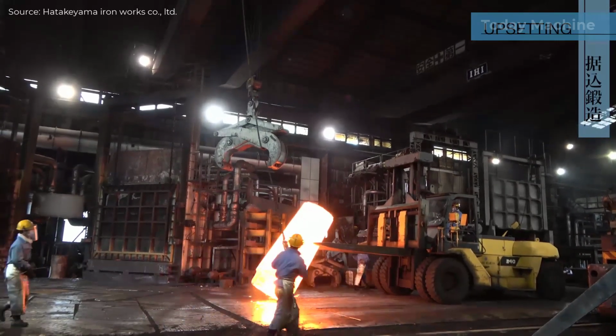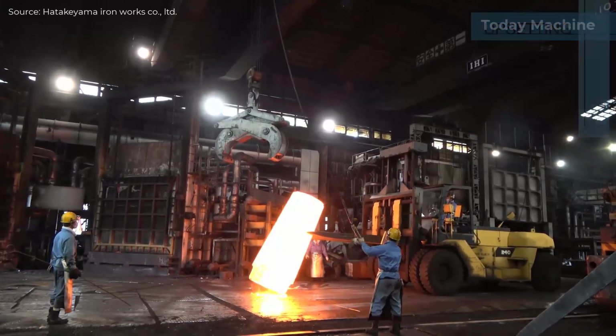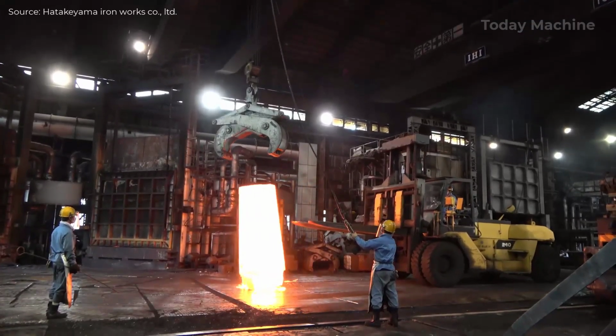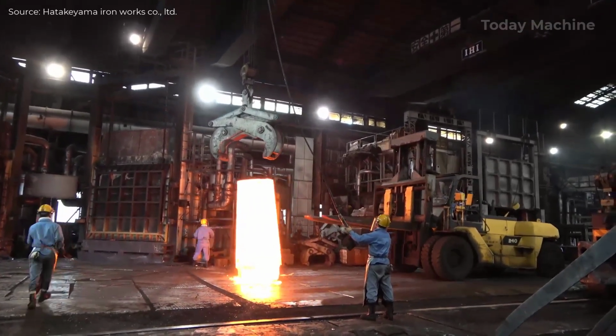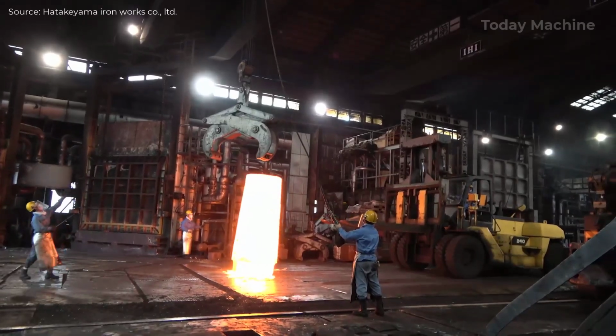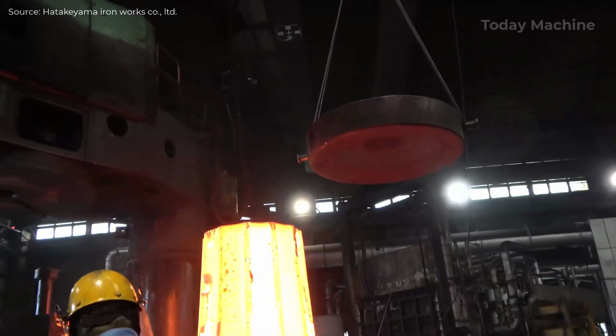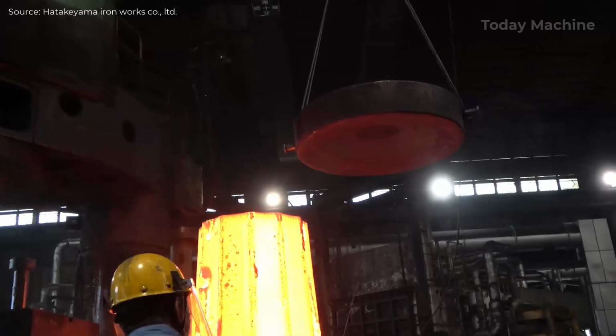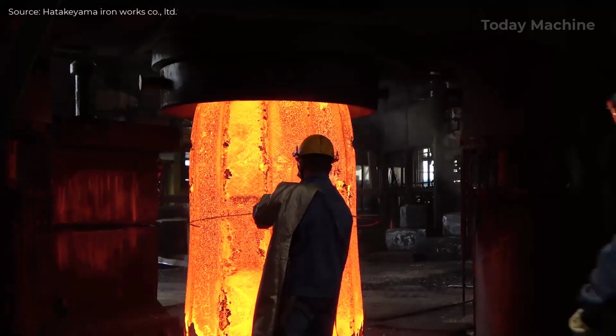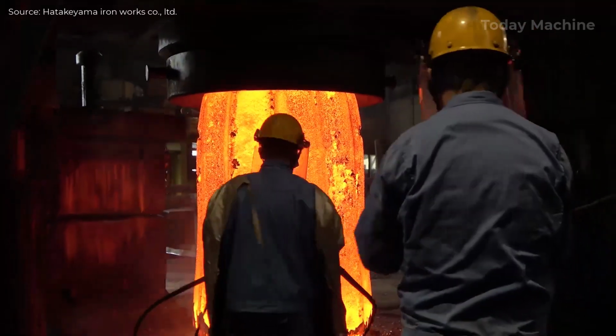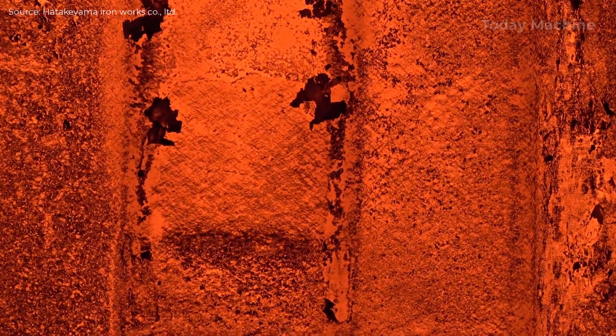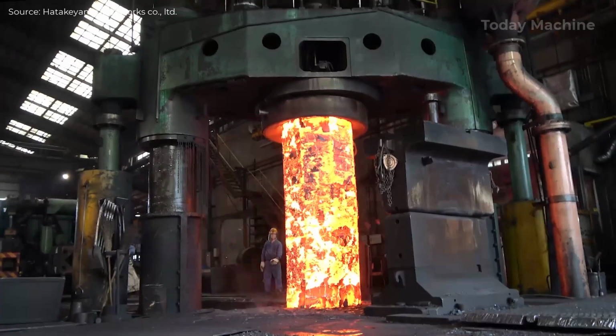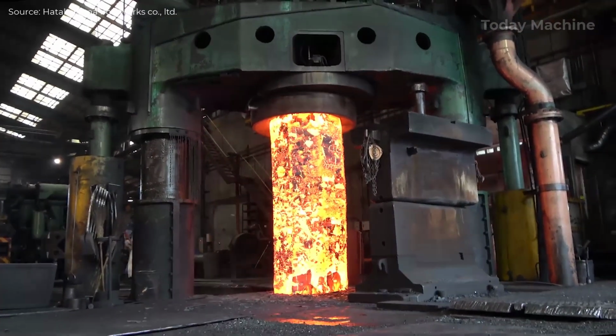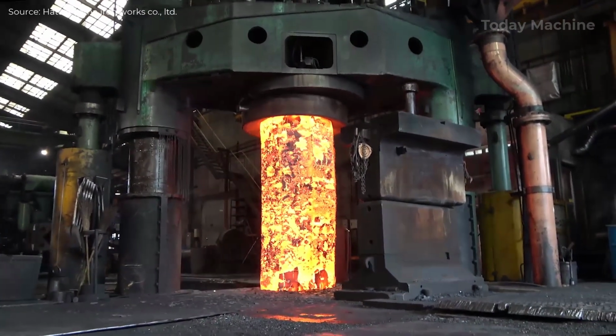Upset forging is the process where the billet is compressed in the axial direction, increasing its diameter while reducing its length. This process is commonly used for parts that need to have a larger cross-section at one end, such as bolts and fasteners. Upsetting requires precise control of temperature and pressure to ensure that the material flows properly and does not crack. The key is to achieve the desired shape while maintaining the integrity of the steel.